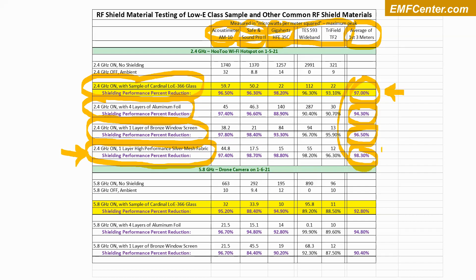But think of all of these as almost the same — they're so close. The differences in actual real-world effectiveness when you put these on a window you're shielding come more from other factors: what also comes through the ceiling, wall, another window, or door; or whether there are any gaps between the shielded glass and the wall. Little gaps allow a lot of signal in. These are relatively good conditions — not quite lab conditions, but close — and these are the shielding properties you can get from these materials.